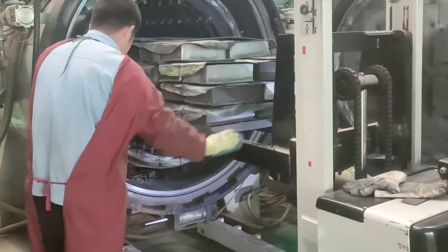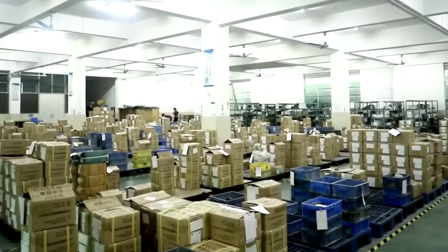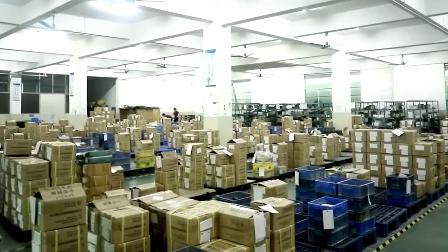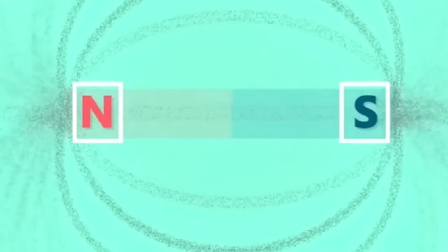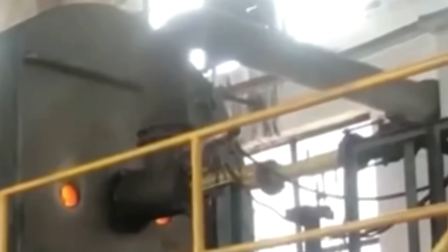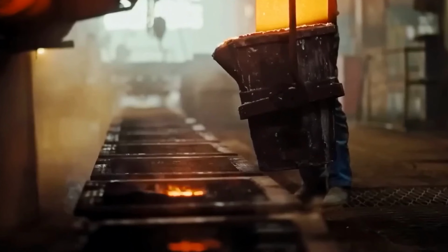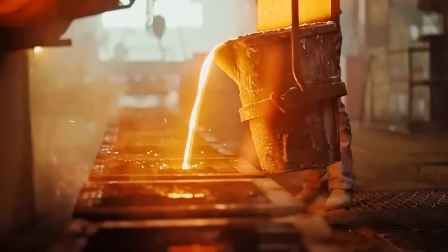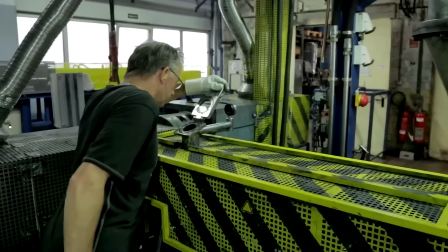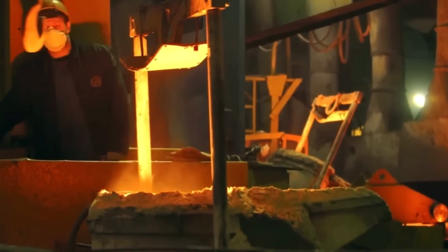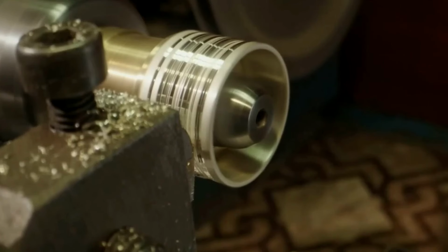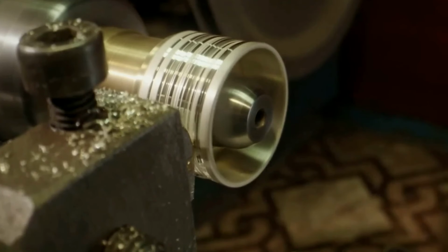The magnetization stage is the process that awakens their true power. Each magnet is placed between the poles of a pulse magnetizer, where an extremely high electrical current, reaching between 2,000 and 3,000 amps, is discharged in just 1 to 5 milliseconds. This surge generates an instantaneous magnetic field with an intensity of about 5 Teslas, tens of thousands of times stronger than the Earth's own field.